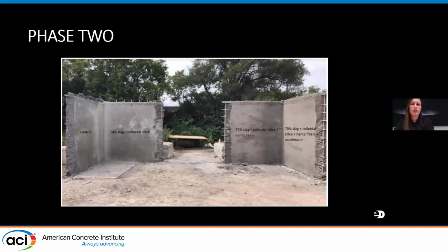These were the 4 final walls in one of the trials. In regards to the finishability of the 4 shotcrete mixtures, some mixtures stood out over others, with the heat of hydration developing quickly for the control mix, which is on the left. As expected, the finishing operations had to be performed relatively quickly to ensure that the surface could be troweled and finished smooth. The mix which contained 70% slag and the nanosilica showed signs of tearing at the surface and bleed bubbles or blisters due to, I think, prematurely finishing it.